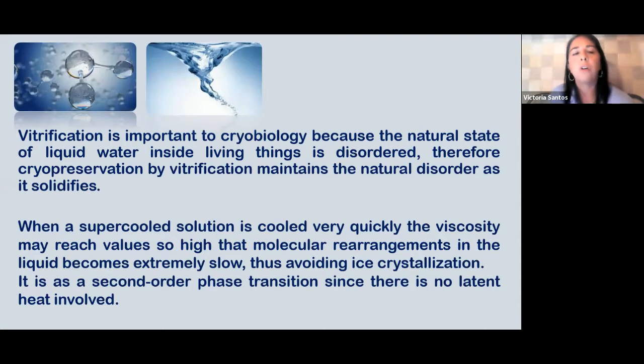Everybody knows what happens to samples when they are frozen slowly, and when they are frozen at high cooling rates. So I'm just going to dive into vitrification and tell you something about it. Vitrification is important to cryobiology because the natural state of liquid water inside living things is disordered. Therefore, when we vitrify, we maintain this natural disorder as the sample solidifies. How do we do this? Well, we have a supercooled solution that, when it's cooled very quickly, the viscosity may reach very, very high values. So if we do it quickly, we do not allow the molecular rearrangement into a crystal structure. Therefore, we avoid ice crystallization.